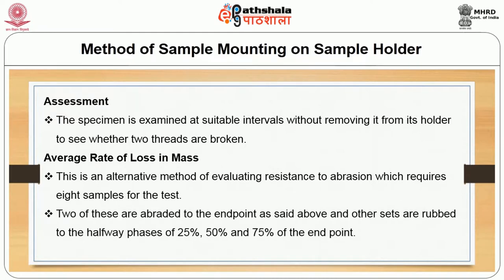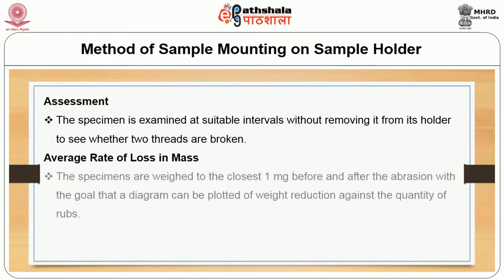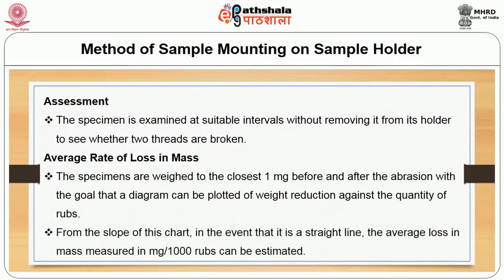And the other sets are rubbed to fractions of the endpoint, such as 25%, 50%, 75%. Specimens are weighed to the closest 1 milligram before and after the abrasion, so that a chart can be plotted of reduction in weight of the woven fabric against the number of rubs. The slope of the chart gives us, if it is a straight line, the average loss in mass, measured in milligrams per 1000 rubs.